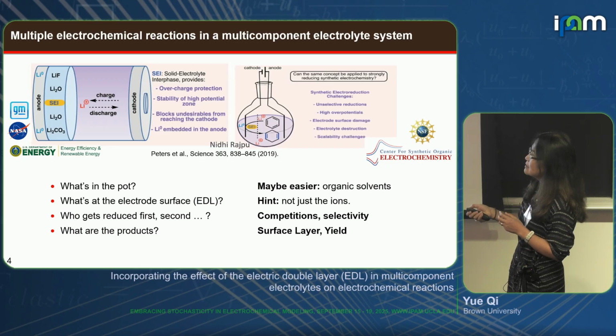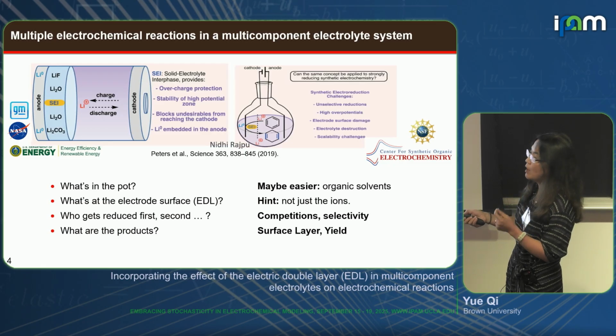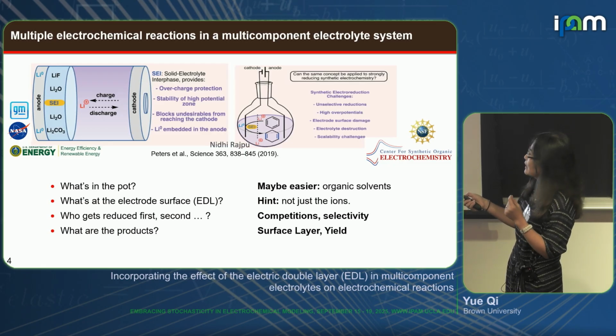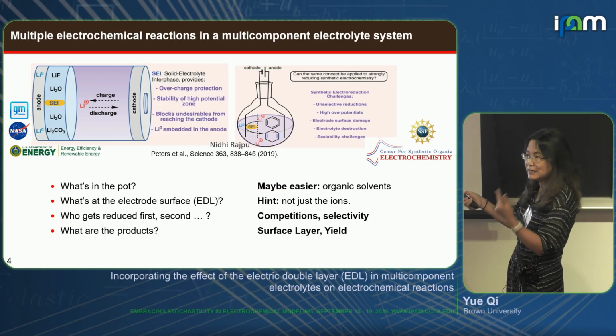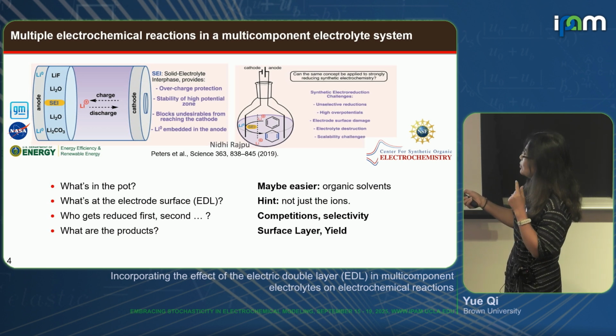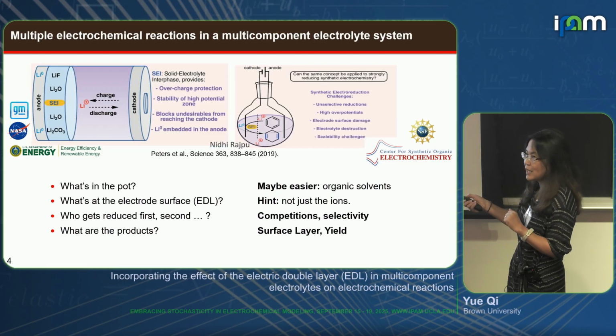But in this case, the reduced particles can form a passivation layer on the surface. And this layer, we want them to transport ion but to block electron. And this layer, we can't really block electron because we continuously have the electrochemical reaction, but we also want some partial protection of the surface.